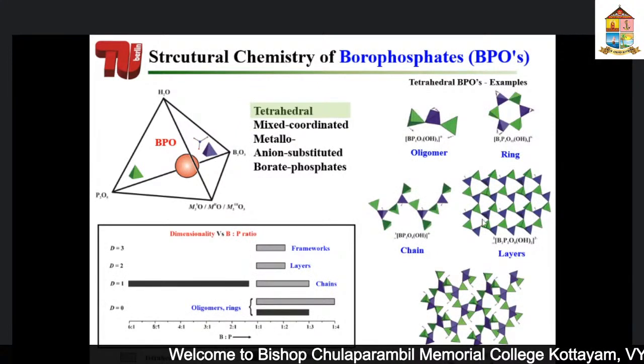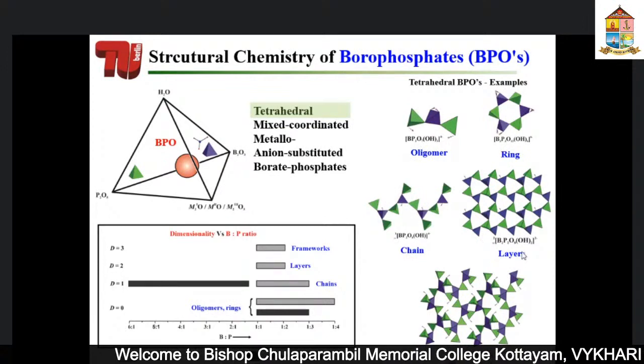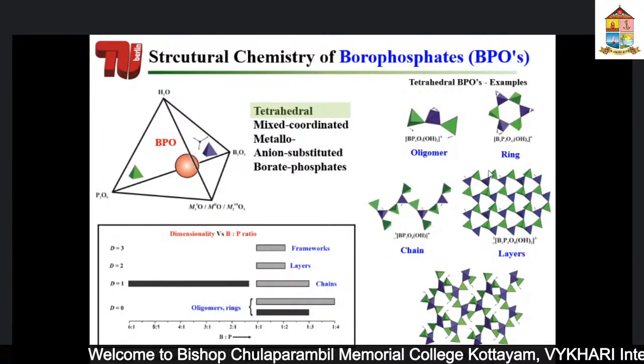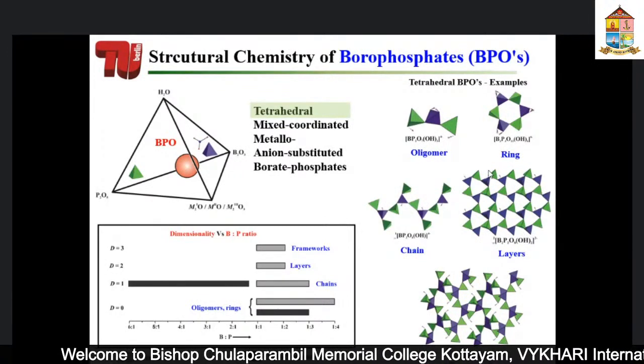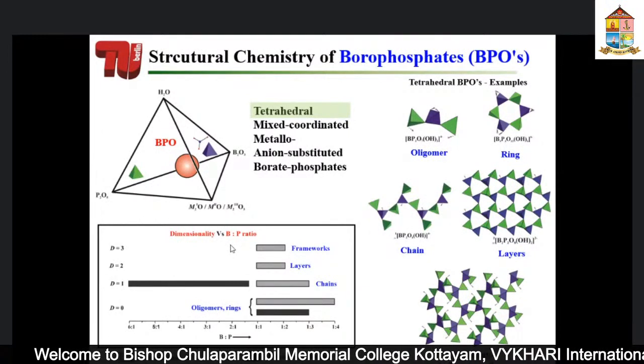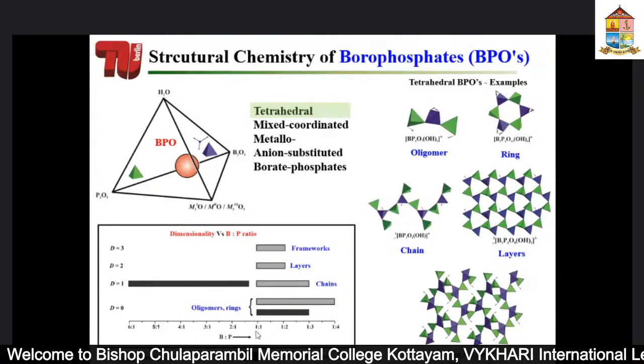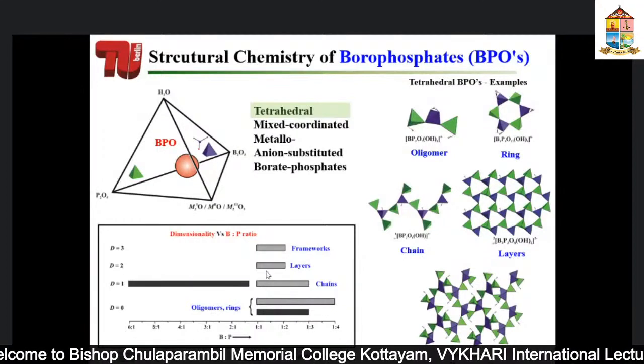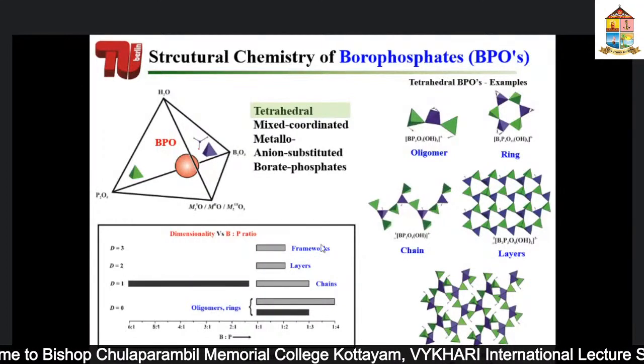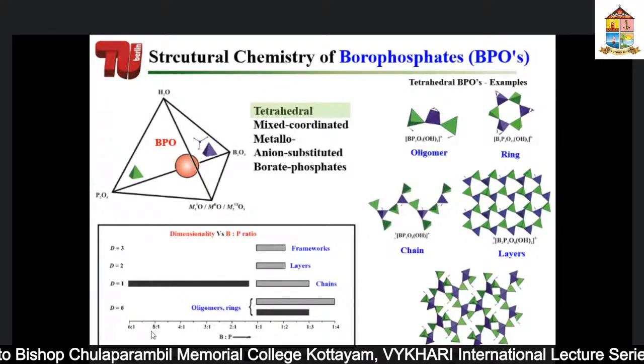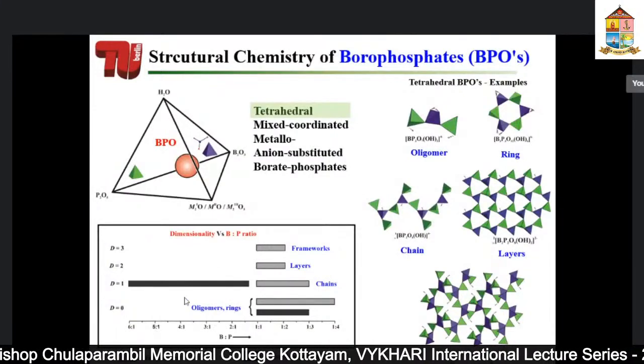You can see some different architectures which can form oligomers, rings, chains, layers, and frameworks. They can be further connected with the metal octahedra to form a three-dimensional network. Just simply to show you how the whole thing works, you can increase the phosphorus ratio and you can form different architectures or different dimensionalities. And if you use the borate, or let's say boron ratio, you could still form, let's say, only a chain structure, which is probably not important at this point of time. What is important is what we are doing at the moment.